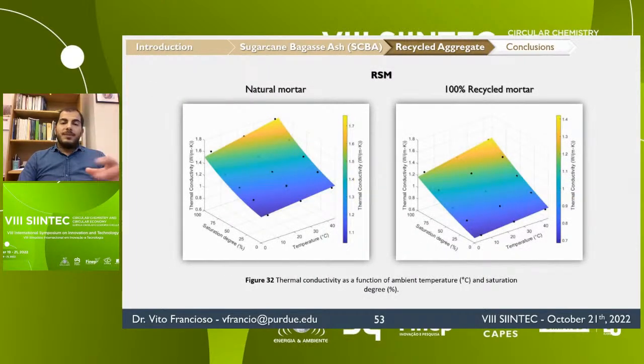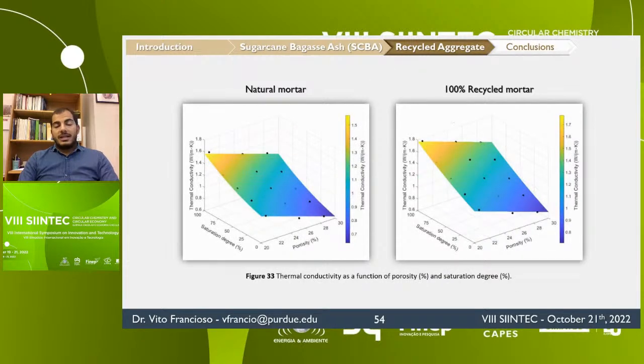Also, we used a response surface method to study the combined effect of saturation degree and ambient temperature on the mortar's thermal conductivity. In these graphs, the points represent the experimental results, while the surface represents the estimation. As we can see, the thermal conductivity increases with both moisture content and temperature. However, the influence of the saturation level, or moisture content, is more important. The response surface method was also performed to assess the combined effect of recycled concrete aggregate, in terms of permeable pore space, and the saturation degree on the thermal conductivity of mortars.